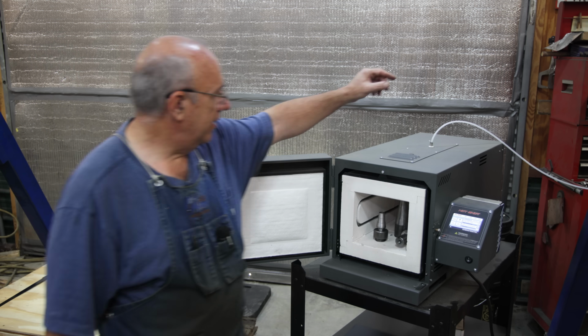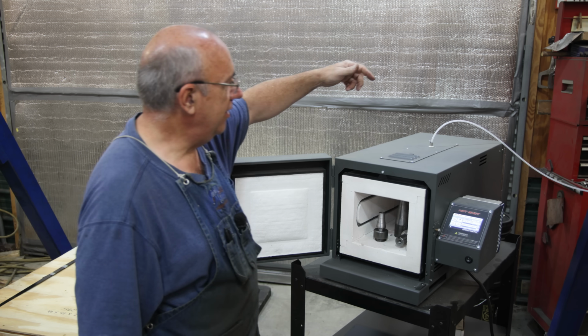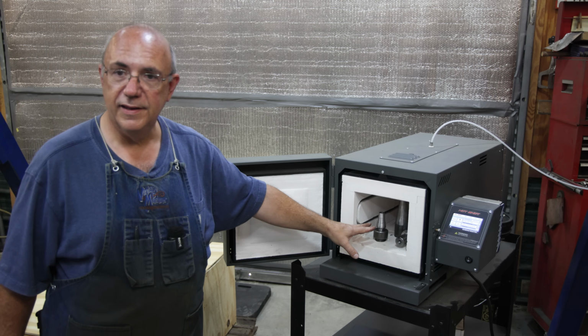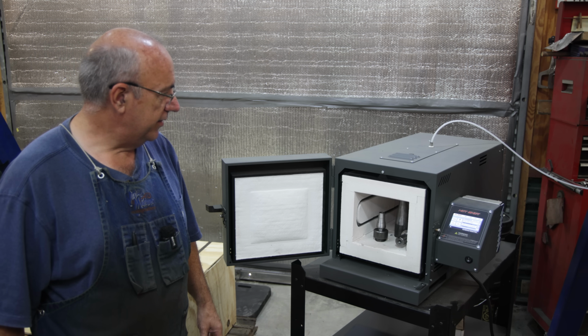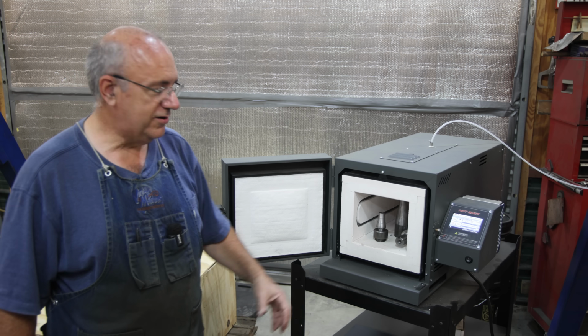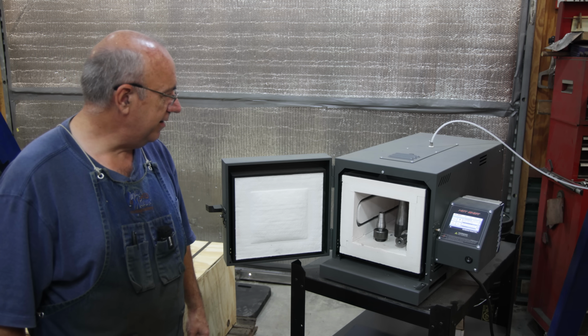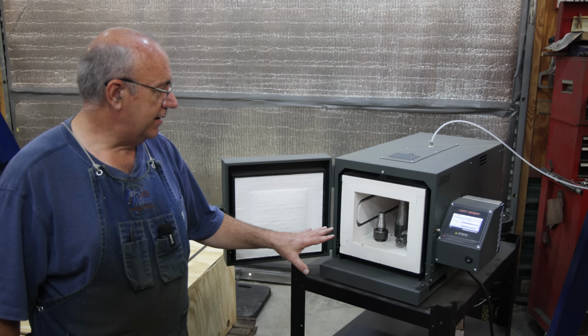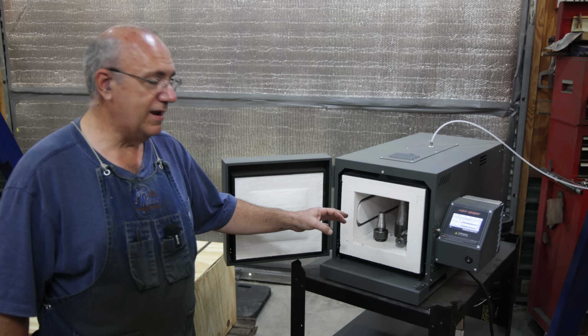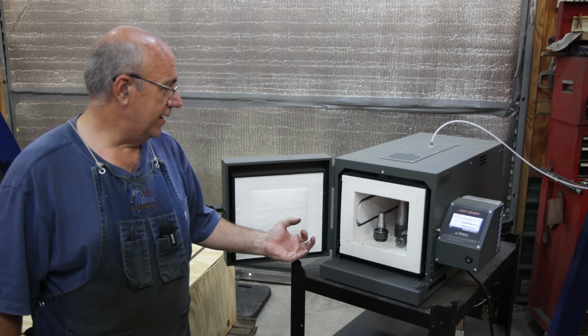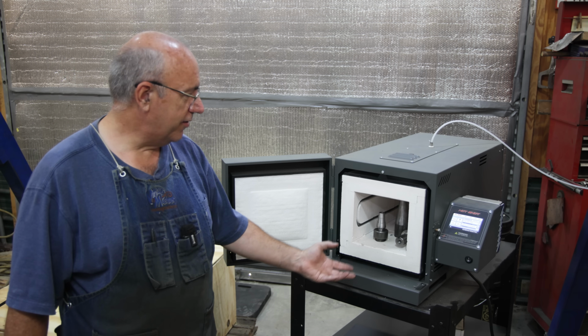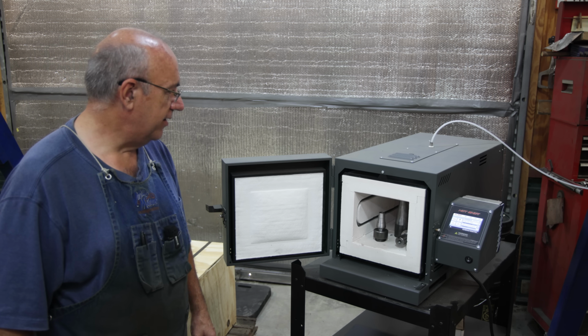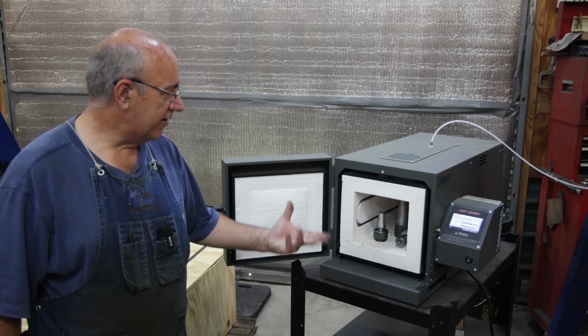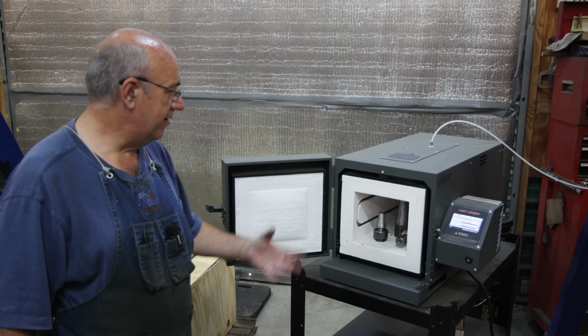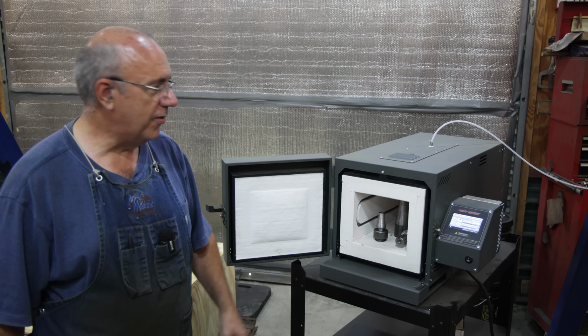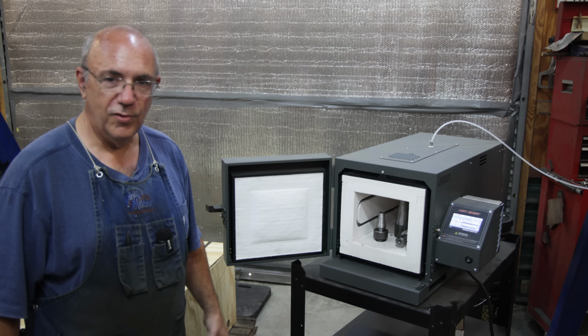I'll also note this little, I got a hose coming in here. I'm actually flushing argon into the oven, and when I close this, I'm going to leave the front door cracked for just a few minutes to make sure we purge all the oxygen out of there. Then I'll seal it up, and the argon basically is an inert gas, the same as you use for TIG welding. And the idea there is that you won't get any oxidation or greatly limit the amount of oxidation that goes on inside the oven while you're doing your heat treat. When you get the oxygen there, you get that scale on the outside of the steel. The idea here is if we remove all the oxygen from the oven, we purge it with the argon, you won't get the oxidation going on.